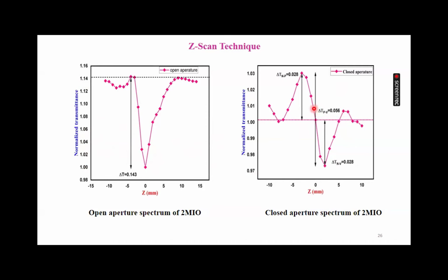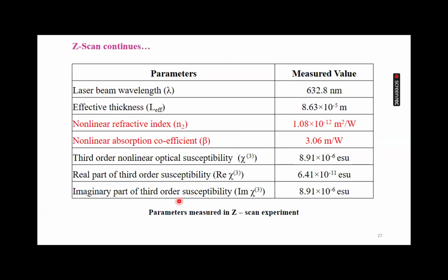The measurement of the peak was performed, which is shown in the figure. The upward transmittance peak value is 0.028 and the downward direction transmittance value is 0.028 with the corresponding same values. Finally, other properties were measured, such as those confirmed for NLO materials: the nonlinear refractive index value is 1.08 × 10^-12 square meters per watt. The nonlinear absorption coefficient value is 3.06 m/W.